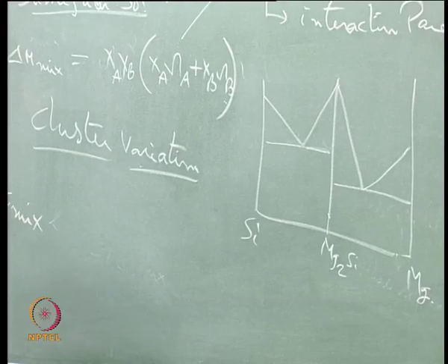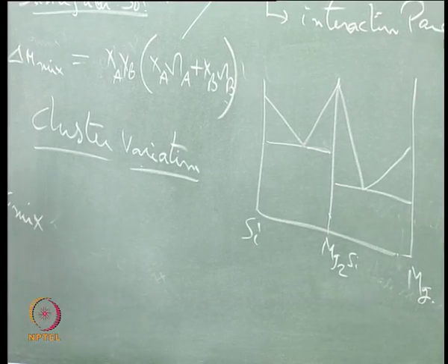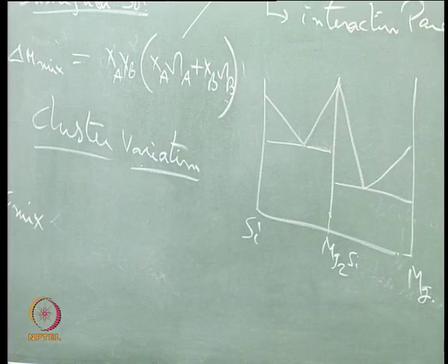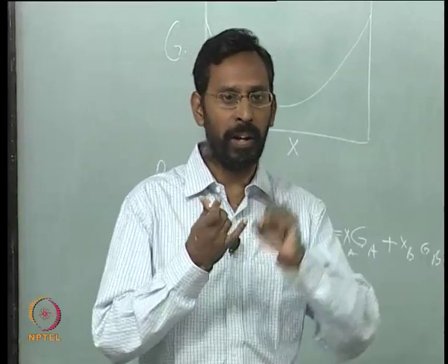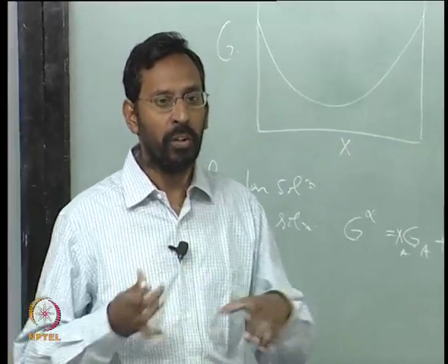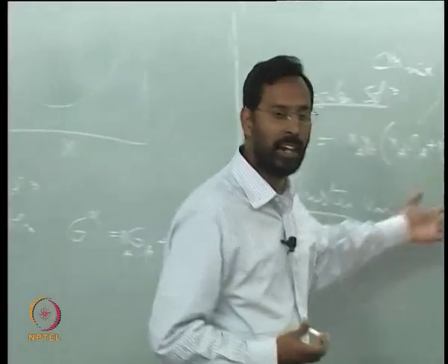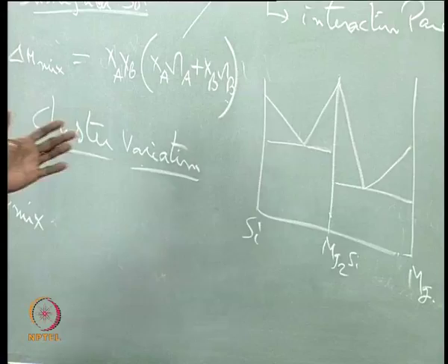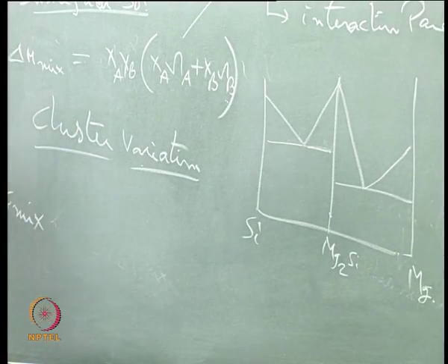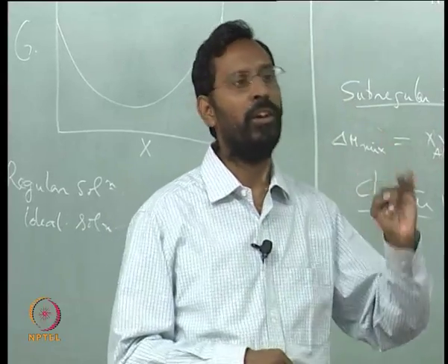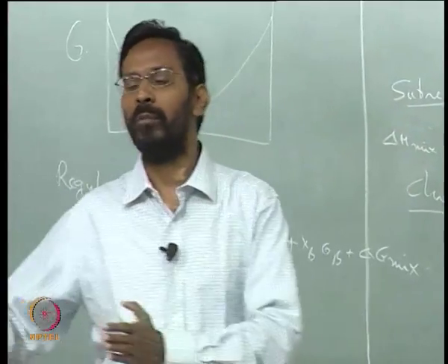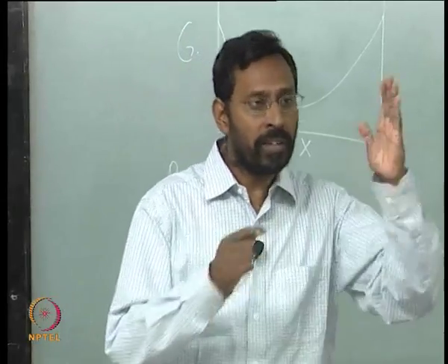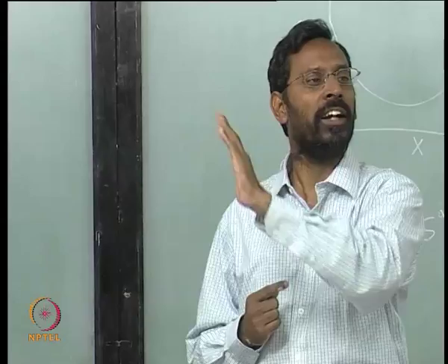So, find out various possibilities of clusters and compute, based on the electronic configuration and the atomic sizes, which cluster has the lowest energy, and from that one can find out what the possible compounds are. And in some systems there are in fact more compounds. If you take for example the aluminum nickel phase diagram, you have Al3Ni, you have AlNi, you have Ni3Al and a number of other compounds too. So that means at specific positions you suddenly start getting intermetallic compounds.